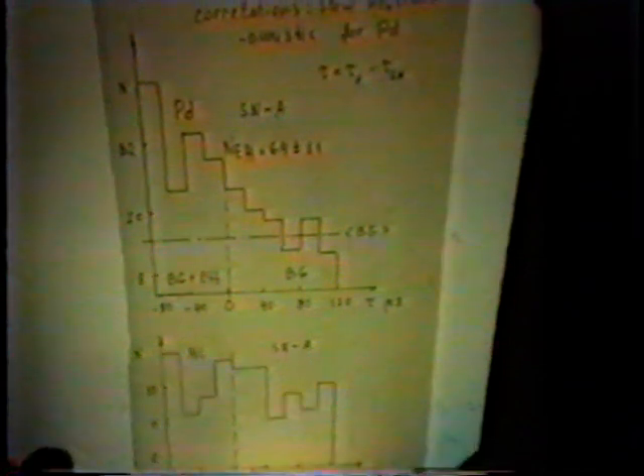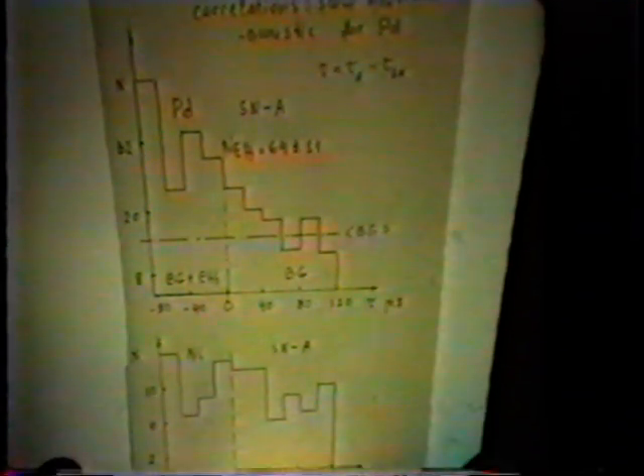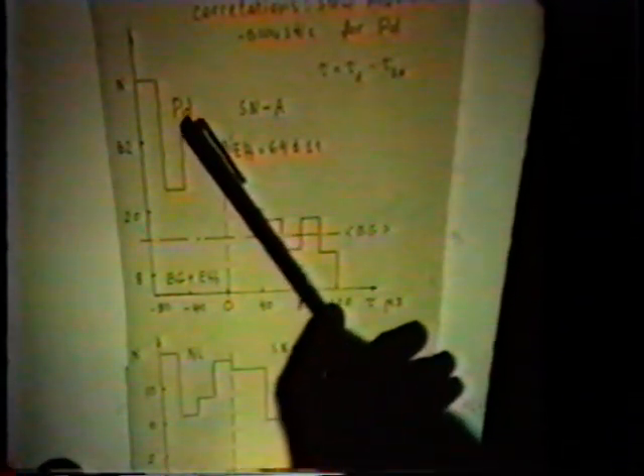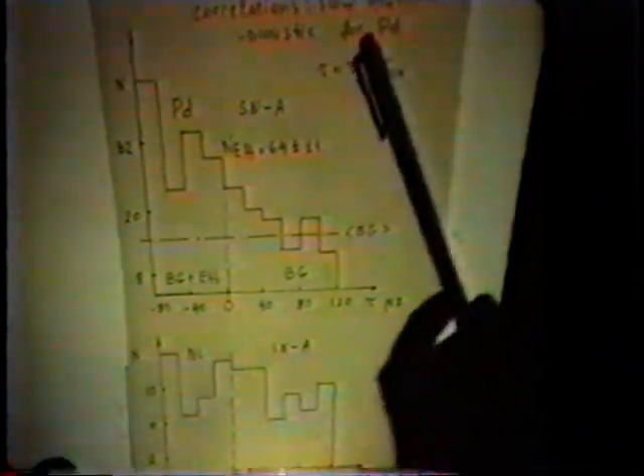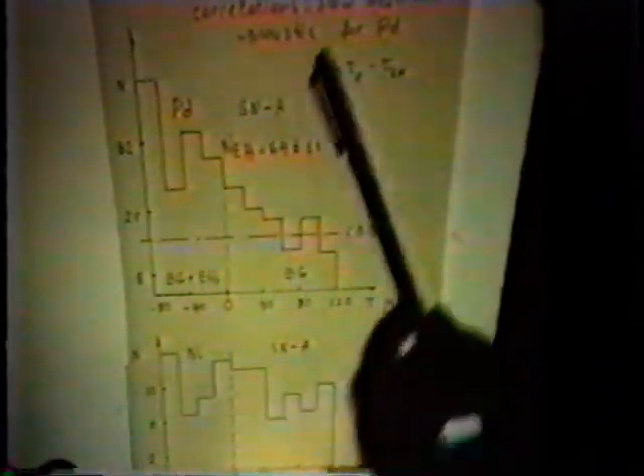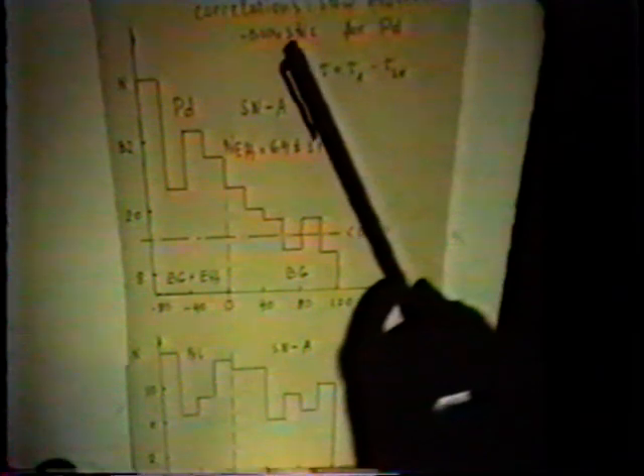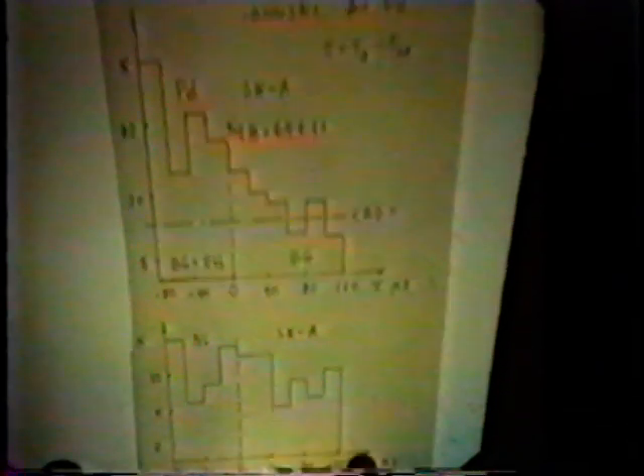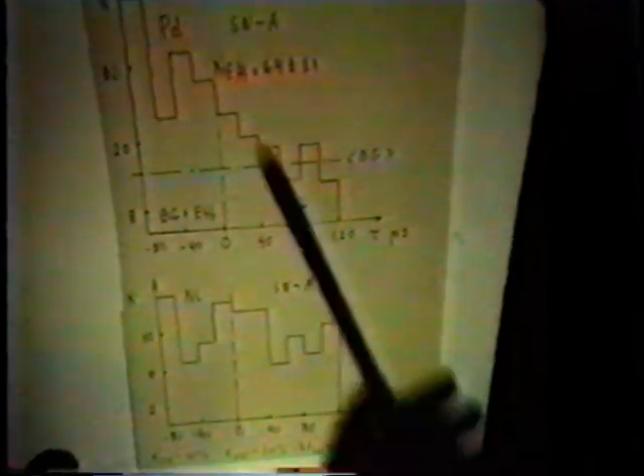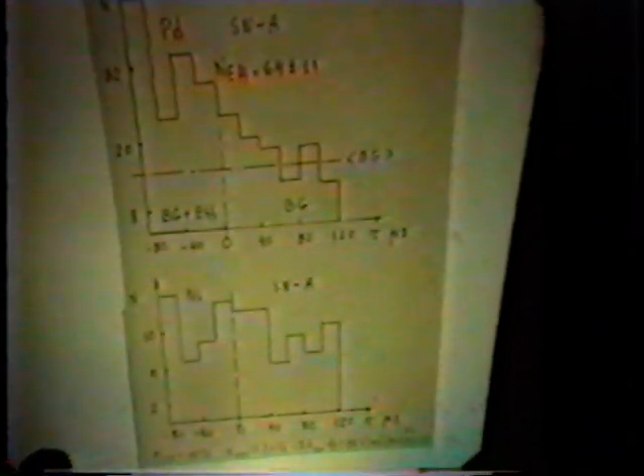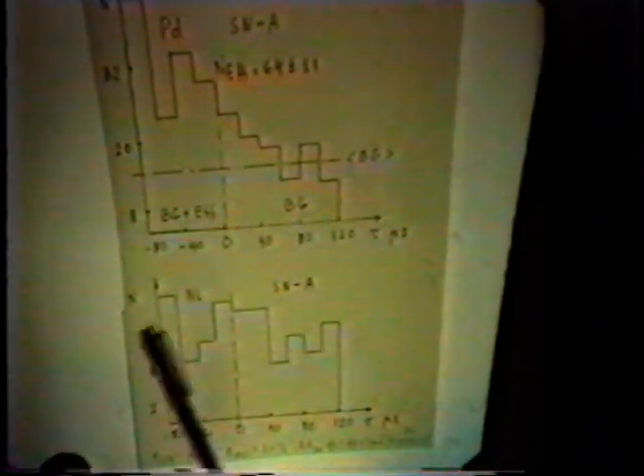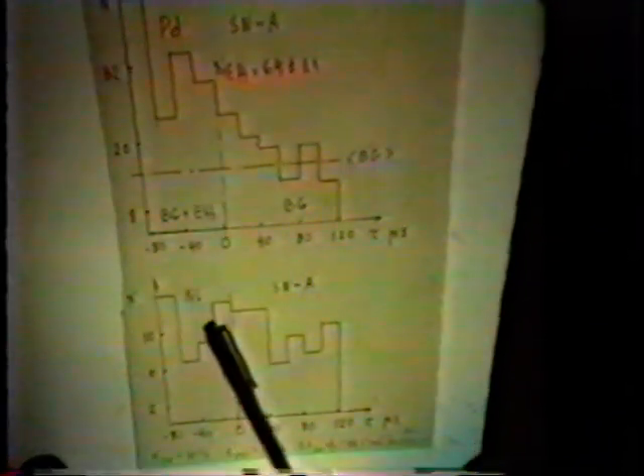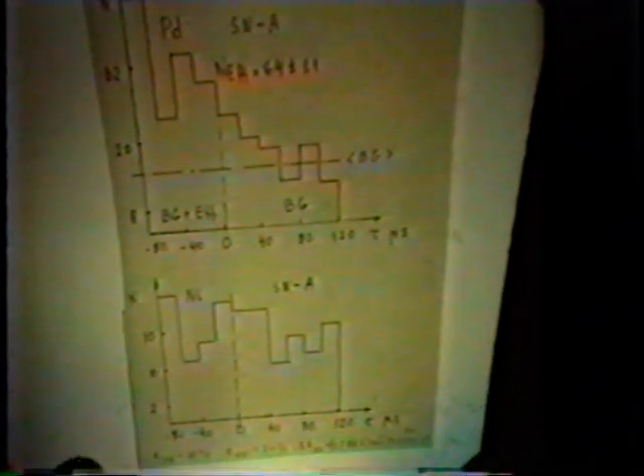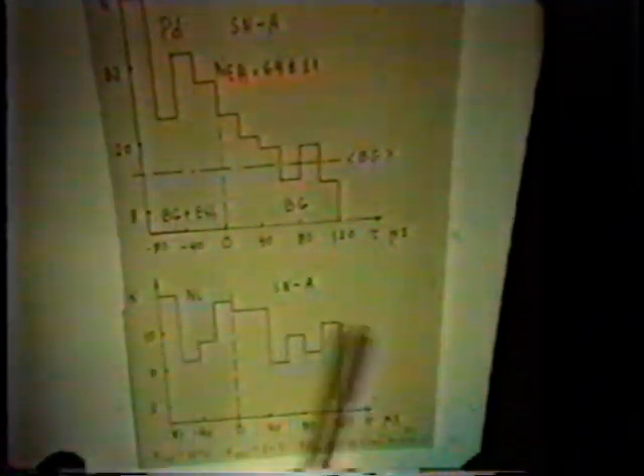This is the distribution of correlation times taken during electrolysis with a palladium cathode. There was a correlation between slow neutron and acoustic signals. And you can compare this curve with the blue curve, which was taken in just the same way, but not with palladium, but with a nickel cathode. And you see that in this case there are no correlations.